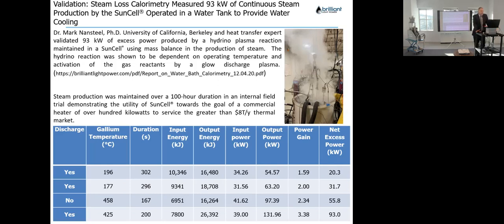Subsequently, and particularly in the cell that you observed today, we've added carbon liner, we added refractory metal liner, and that cell can run at much higher temperature. This internal temperature was around 425. The one we ran just now was more like 750, and the power more or less doubles over that temperature increase.